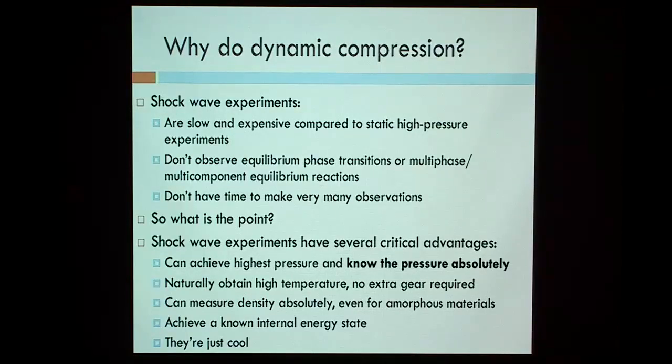Okay? And that works even for amorphous materials where you can't do diffraction, which is the basic technology for measuring densities of materials in static experiments. The next thing is, because a shock is an adiabatic change of state, we have exact knowledge of the internal energy of the shock state. And that is a thing, an energy, that there is no way to measure in static experiments.